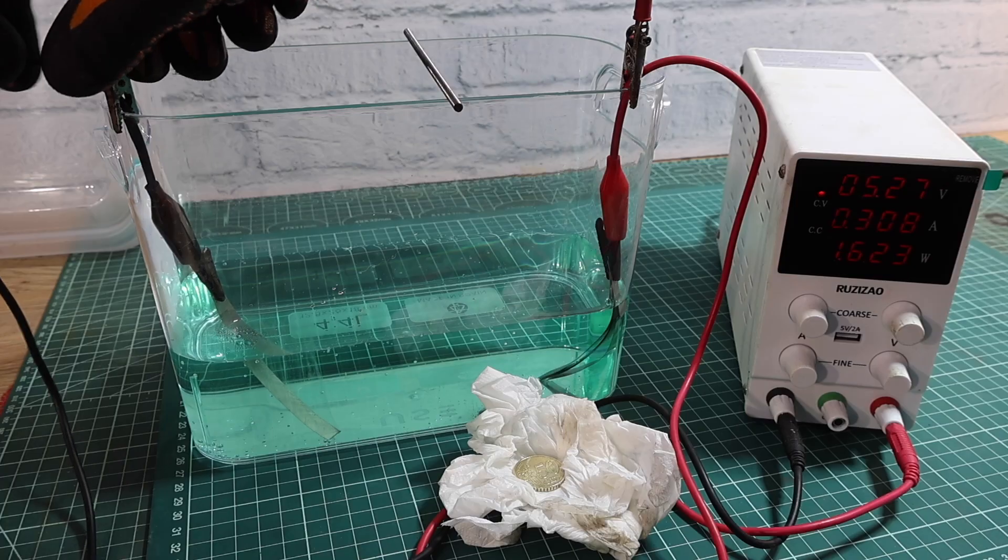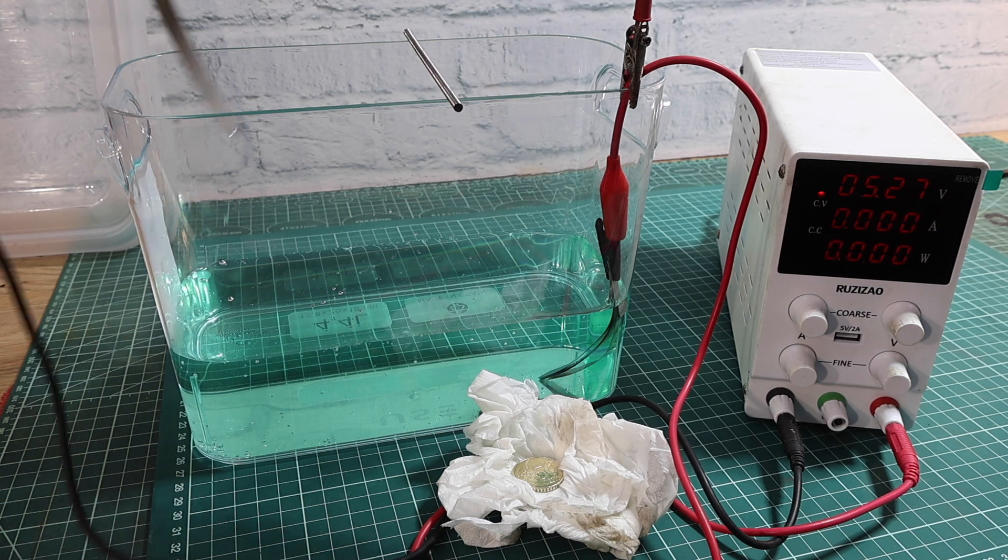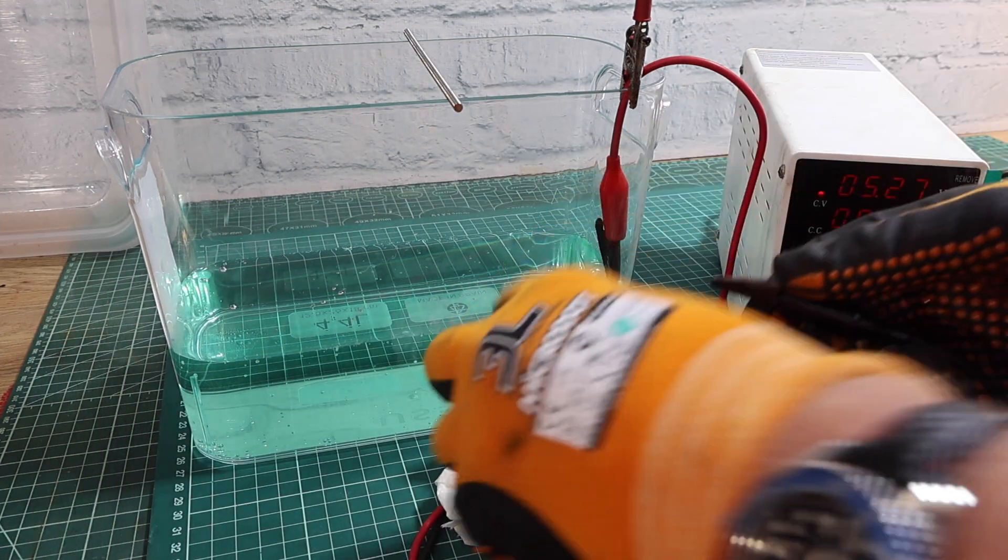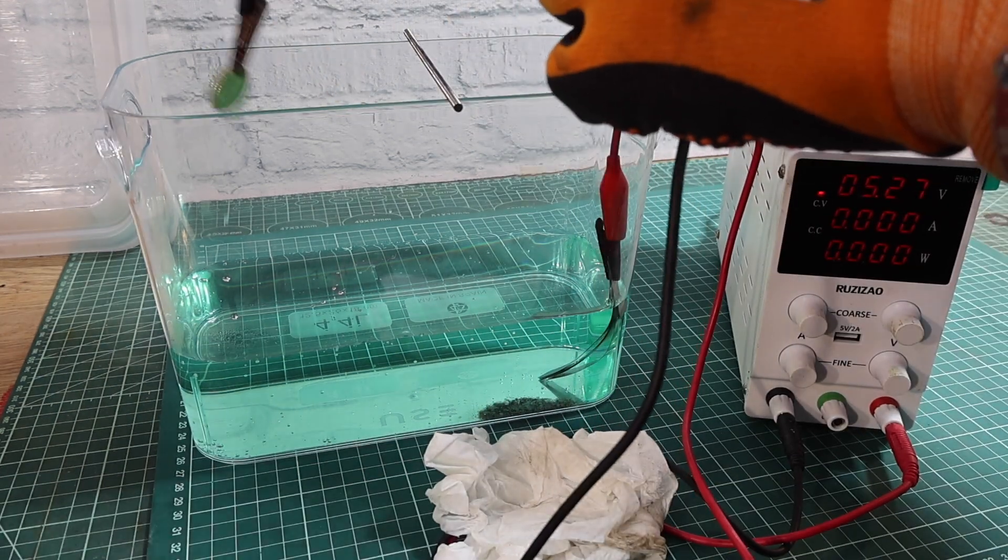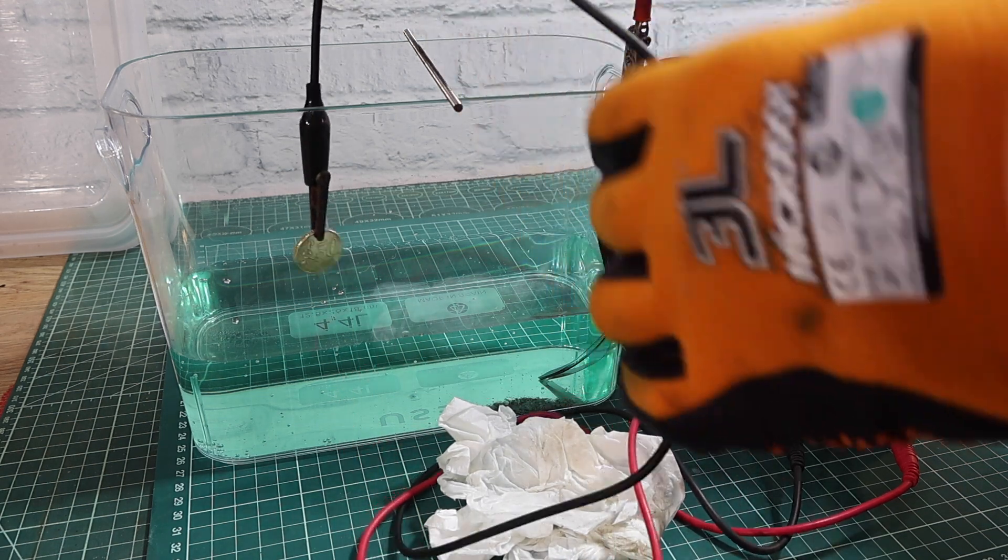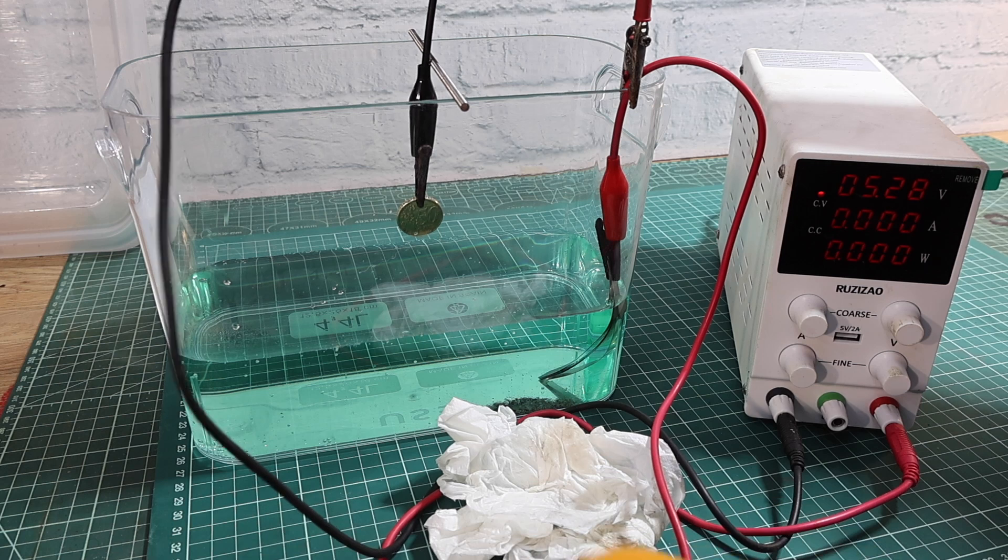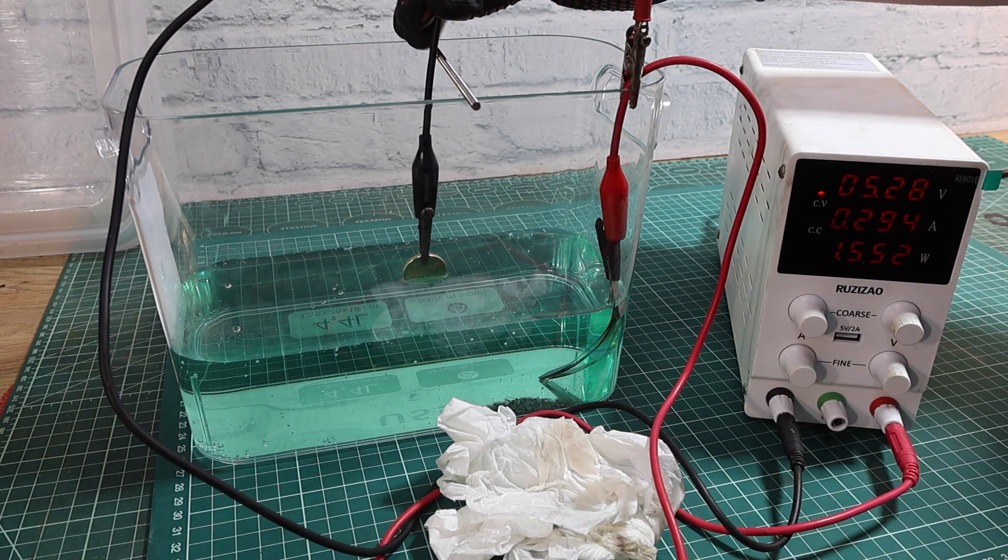And we're going to try, the first thing we're going to do is use a coin. So we have to remove the strip on the negative side. Keep the nickel strips on the positive side. You will note that I cleaned the coin. I used acetone actually. But it wouldn't be good to touch it with your fingers. It would put some grease on it and give you a plating problem. So this coin now is attached to the negative side. I just need to clip it onto this support I've got.